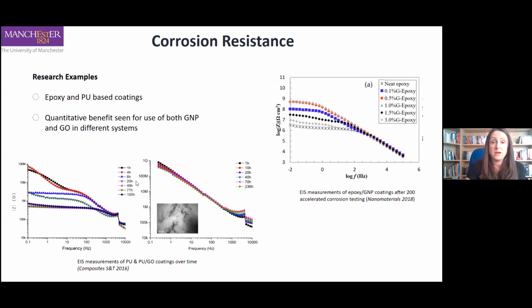And what you see here is for the neat epoxy coating down here, the values are very low. It doesn't do well in the test at all after 200 hours. But if you go up and you look at these high lines, about 0.5, 1% weight inclusion of graphene shows a really high impedance modulus value. Even after salt spray testing, it's up about 10 to the 9. And that's really very good compared with the neat epoxy.